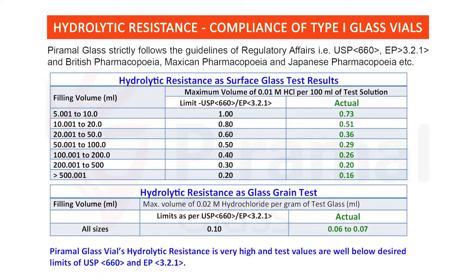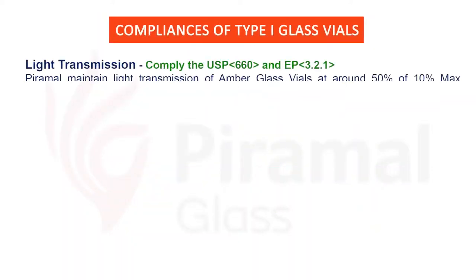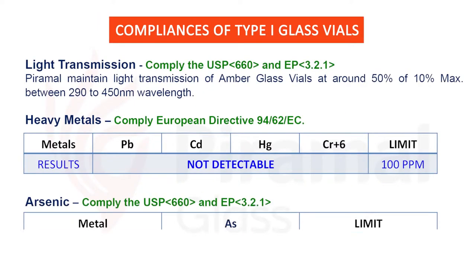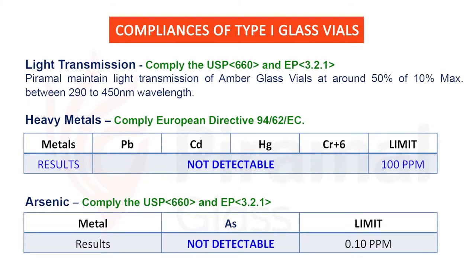like heavy metal, arsenic and elemental impurities as per ICH Q3D and USP 232. Piramal Type 1 vials are in compliance with heavy metal European Directive 94/62/EC and arsenic. Piramal Type 1 amber vial light transmission is in compliance with USP 660 and EP 3.2.1 requirements between 290 to 450 nanometer wavelength.